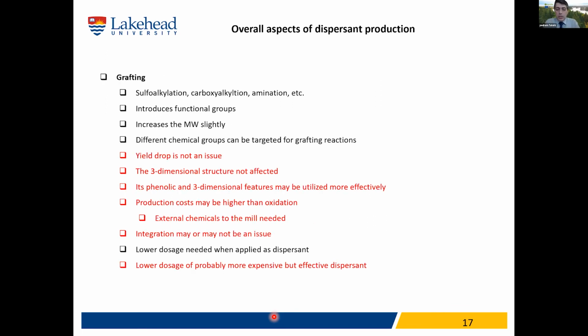How about grafting? Again, we have done a lot of sulfoalkylation, carboxyalkylation, amination. You can introduce many different charges, not just carboxylic groups. They increase the molecular weight a little bit, not too much. Different chemicals can be targeted. So you can target phenolic groups, you can target aliphatic groups, you can have different chemistry. Yield is not an issue because you are adding chemicals to lignin. You are not decomposing or degrading or basically cleaving the lignin.